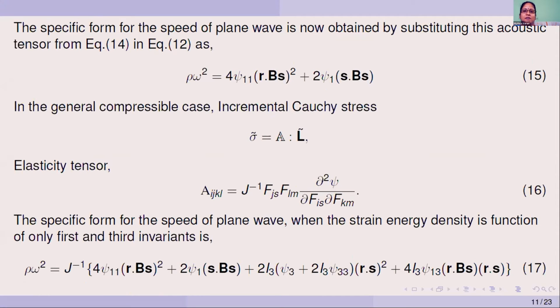And this equation is valid only for incompressible materials and when the strain energy density is a function of only the first strain invariant. In general, for a compressible case, the expressions for the incremental Cauchy stress tensor and the elasticity tensor in component form are as shown here. And this is a specific form for the speed of plane wave when the strain energy density is a function of only the first and third strain invariants, I1 and I3. Here psi33 and psi3 are the second and first derivatives with respect to the third strain invariant I3, psi13 is a mixed derivative with respect to the first and third strain invariants, and this J is the square root of the third strain invariant I3. So this is the equation for the wave speed for a general compressible case.